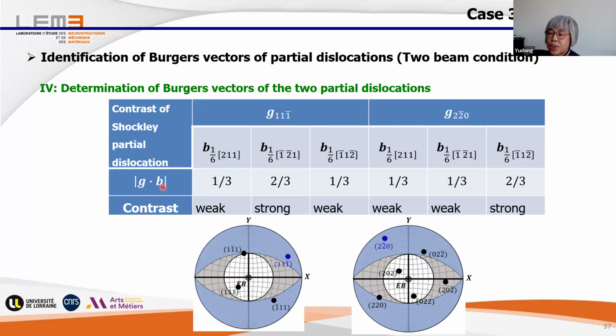For partial dislocations, it's a little bit specific, because for perfect dislocations we have a contrast index of either 0 or 1. But for partials, we have 0 to 1, passing through 1/3 and 2/3. But fortunately, the contrast is proportional to these values. And so the larger the value, the higher the contrast. And so he found this reflection plane.